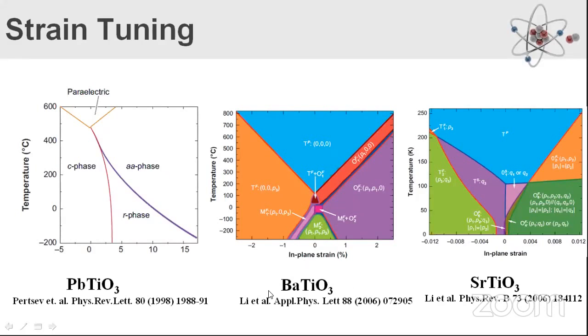Again, if you look at barium titanate, you see the in-plane strain is very small when you compare with lead titanate. Even for a minute strain, this is the ferroelectric Curie temperature, the transition temperature for barium titanate, which is around 120 degrees centigrade without any strain, for a bulk material. If you apply compressive in-plane strain, it changes to a tetragonal structure.